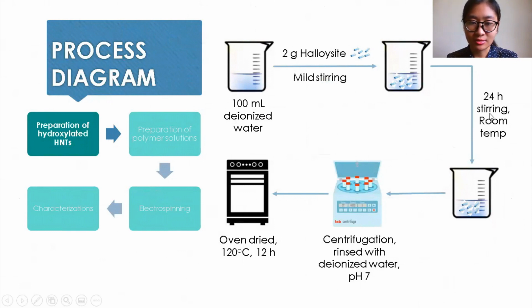As you can see, the alkaline solution is only at 0.01 molar. If a stronger alkaline solution was used, the tubular morphology of HNT was said to be destroyed, according to a journal article. Also, in this step, the siloxane moieties present on the surface of HNT undergo hydrolysis to form